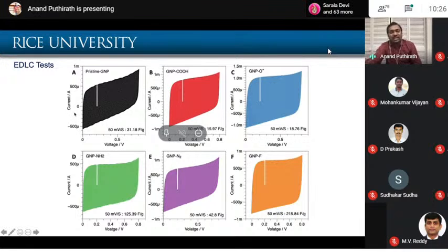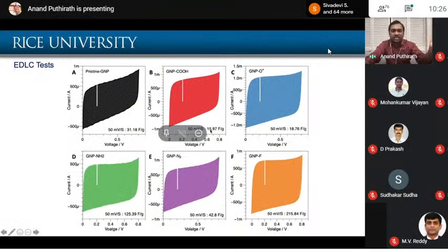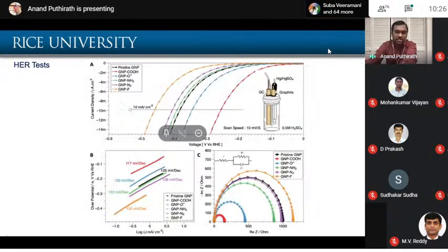And when we did the EDLC test, basically you make electrodes on either side with the functionalized materials and calculate the capacitance. It was quite interesting. Pure GNP has one particular capacitance, and if you functionalize, it varies. With COOH functionalization, it is reduced, and when you fluorinate it, it is increased. I mean, there is a trend that you can see with various functionalizations.